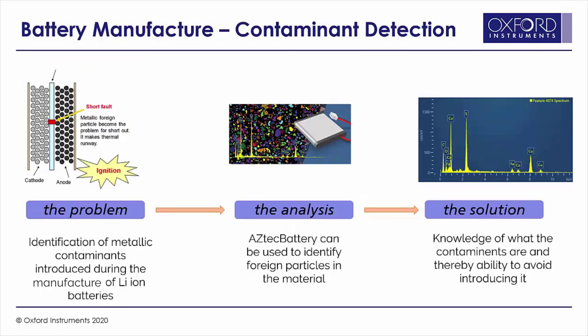Let's now look at an example that's been in the news over the last few years: the presence of contaminants within lithium-ion batteries. If contaminants are present, in the best-case scenario they might just impinge the performance of these batteries, but in the worst-case scenario they can cause shorts and potentially catastrophic failures, including ignition or explosions. It's very important to be able to see if there are contaminants present within the powders used to make lithium-ion batteries. By using automated feature analysis to search over fairly large areas of powders, we can see if contaminants are present, what size they are, and critically what composition they are — enabling us to assess whether they'd be dangerous and to identify their sources.